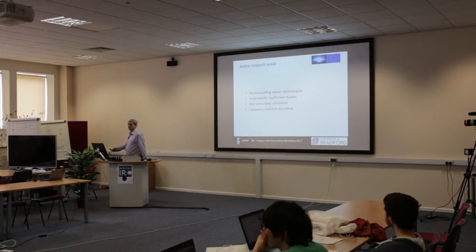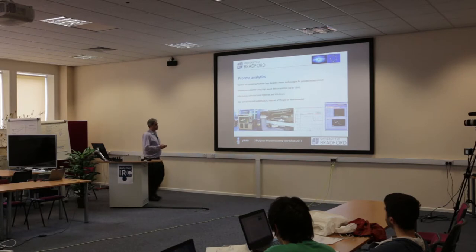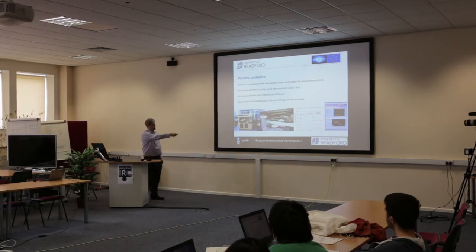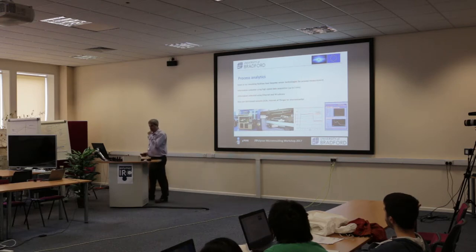I'll look at some research areas dealing with measurement capability — how we interrogate the process to understand what we're doing and troubleshoot to make fundamentally better components. The first area is sensor technologies. On our micro injection molding machine we've installed extra measurement capabilities. One key thing we wanted to understand was the injection kinetics, so we installed a laser displacement sensor on the rear of the injection piston inside the injection unit — a laser triangulation sensor with a target mounted on the back of the injection piston — giving us about 3,000 measurements per second of piston position and velocity.